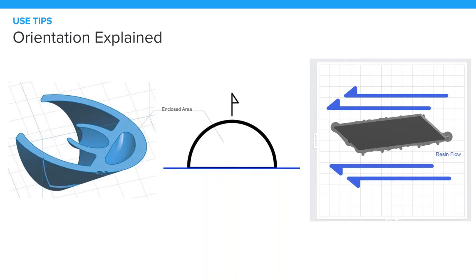Finally, and this is a big one that most people don't catch until it's a couple prints after the fact, and they failed several times. We have an enclosed area that's creating a suction effect, and then yanking the part down, causing a partial or complete print failure. So if any of you have ever played with a Nerf gun or seen an octopus latch onto something, it's a similar effect, where an enclosed cavity pressed against a flat surface will create a suction effect and a resistance to being peeled off.